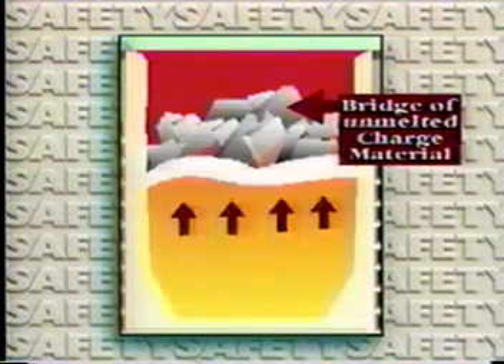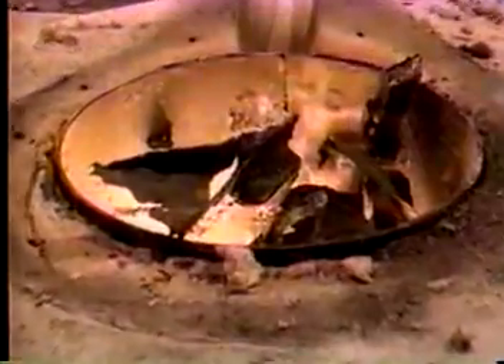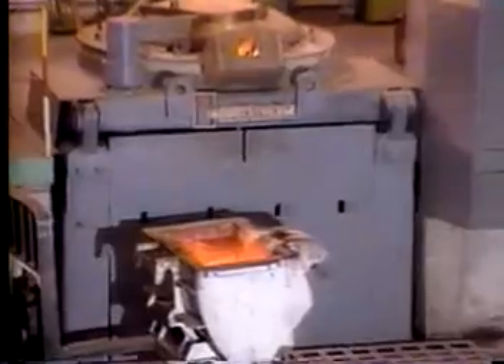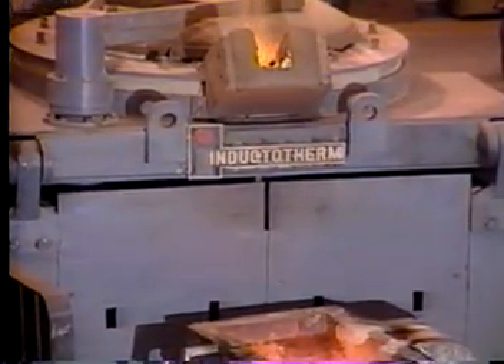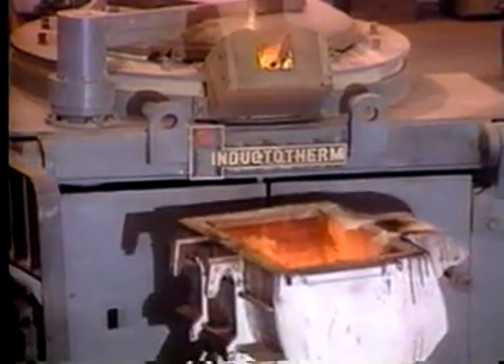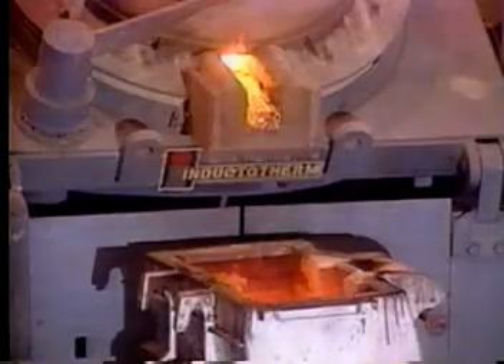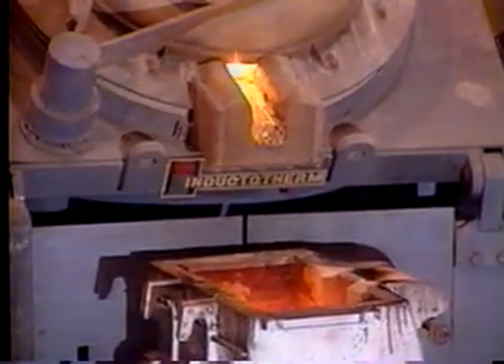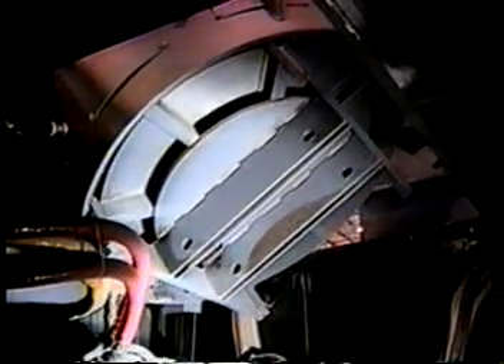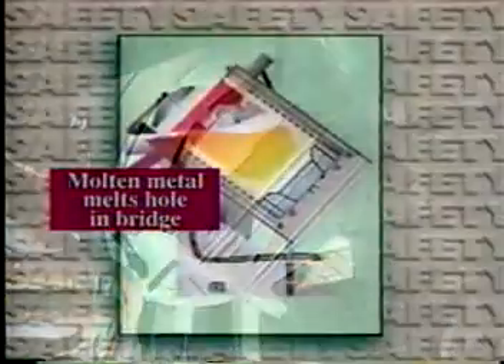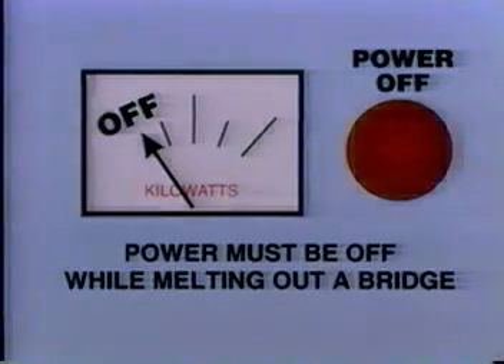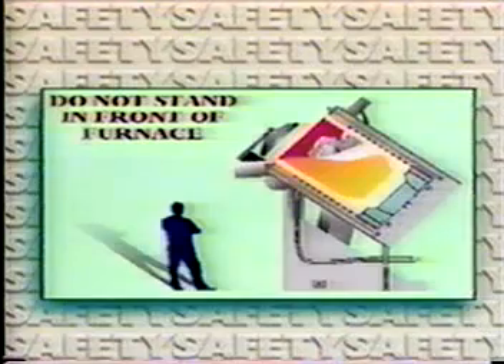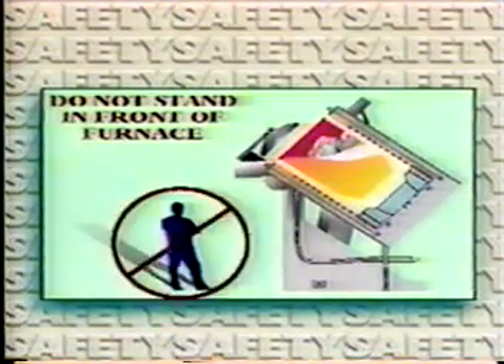If the bridge has completely sealed the top of the furnace, pressure may build up between the molten metal and the bridge. If this has happened, it's safest to allow the molten metal to freeze. If it can be determined that the bridge has not sealed the top of the furnace and that pressure has not built up within the furnace, it may be tilted to attempt to melt out the bridge. Put a ladle in front of the furnace to catch any metal that may spill out. Then tilt the furnace carefully until the molten metal is in contact with the bridge material, approximately 45 degrees. The molten metal will then melt a hole in the bridge. Power must be off while melting out the bridge. All unnecessary personnel should be kept away from the furnace while melting out a bridge.